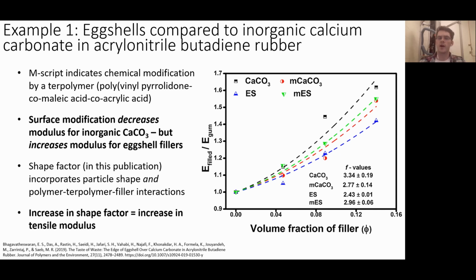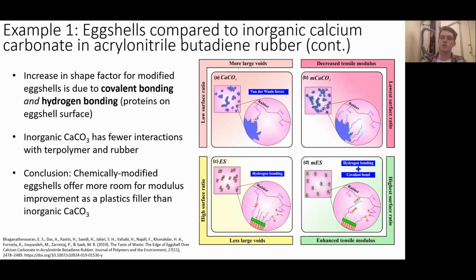So you can see here on the graph on the right, the inorganically derived calcium carbonate did not respond well to the chemical treatment. In fact, the modulus decreased by quite a bit. However, the eggshells responded very well to this chemical treatment. And those composites actually saw an increase in tensile modulus. So the authors attribute this to intermolecular bonding between the eggshells, the chemical surface modification, and the rubber itself.